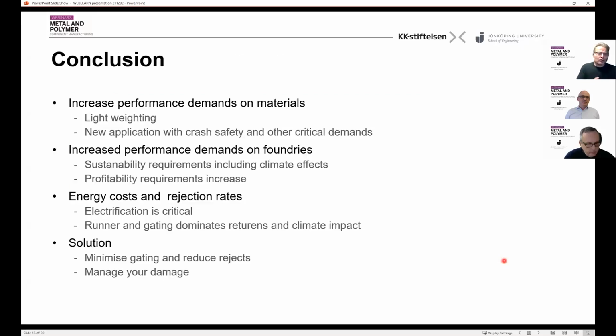So if we try to conclude this in some way, with lightweighting applications, it's seldom so that the load of a component is being reduced, but the requirements on the material are increasing. And there's also a change when you look at the applications of the castings. There are new applications where you have crash safety and other critical demands. That means that we need to manage both porosity and damage in the materials. So ductility and fatigue performance need to be increased. And if you look at the increased performance of foundries, this is essentially also the sustainability requirements. It's not only profitability, you also need to reduce your emissions and your carbon dioxide footprint.